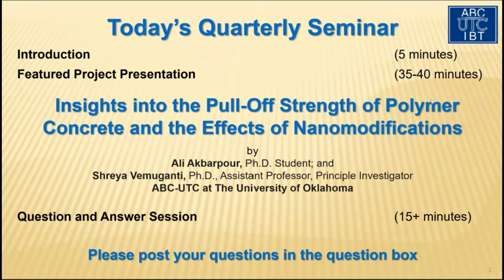But I must say one thing, the guidelines of the overlay itself say that there should be a certain specific strength of the underlying substrate in order for the overlay to actually bond well. So if there are patches where there is not enough strength developed with the substrate, then definitely the engineer should be reached out to and see maybe some other kinds of solutions. Maybe, let's say, if it's a good enough depth for the substrate, the top part can be removed, maybe like an inch or two from the surface, and repaired, and then the overlay can be applied. So those can be possible options.